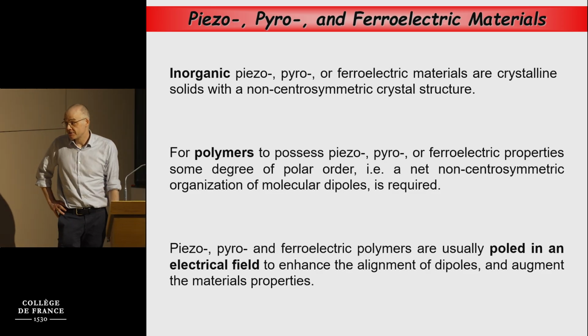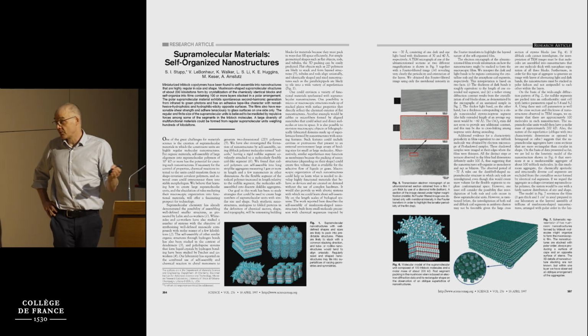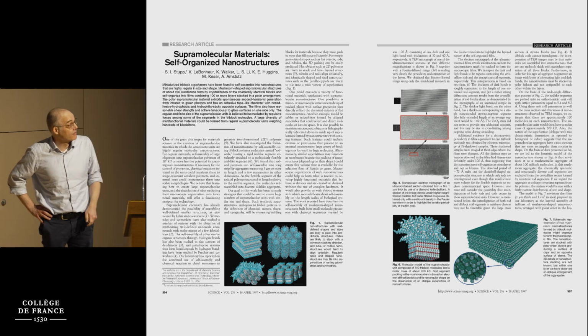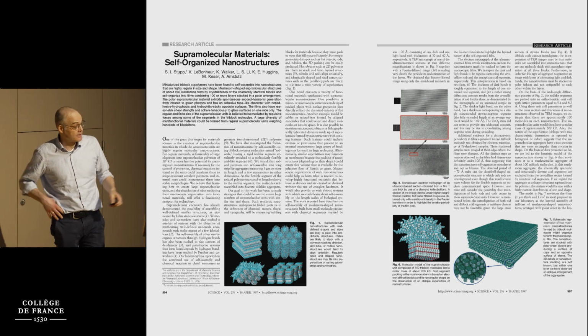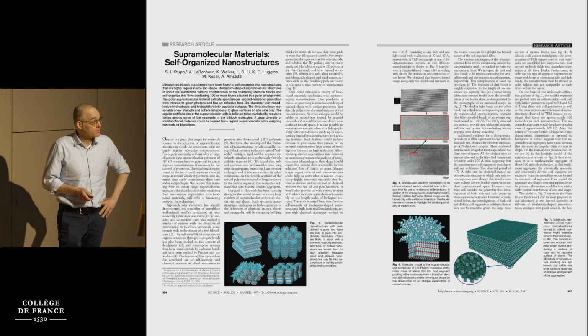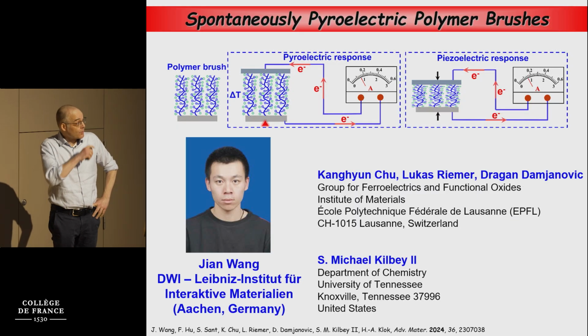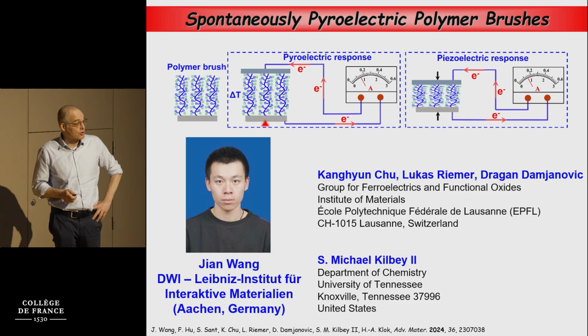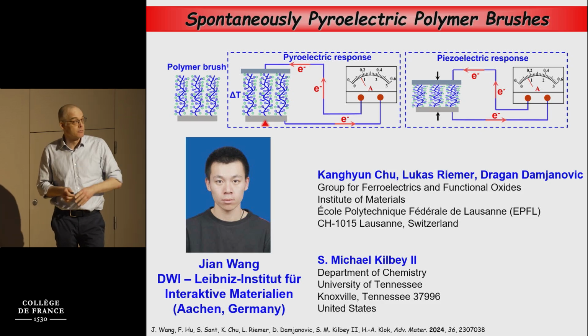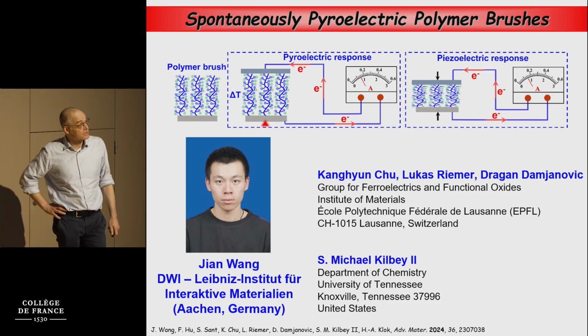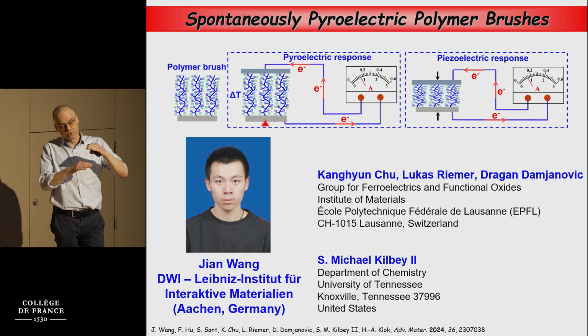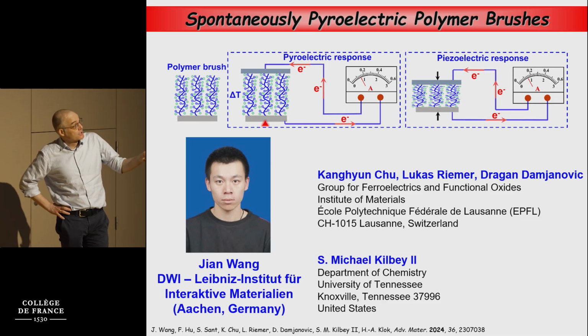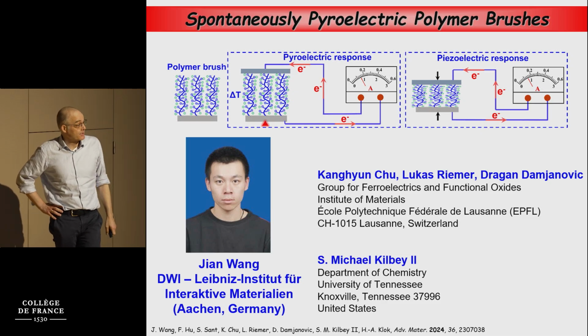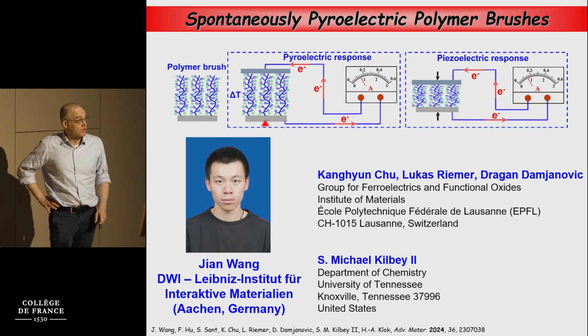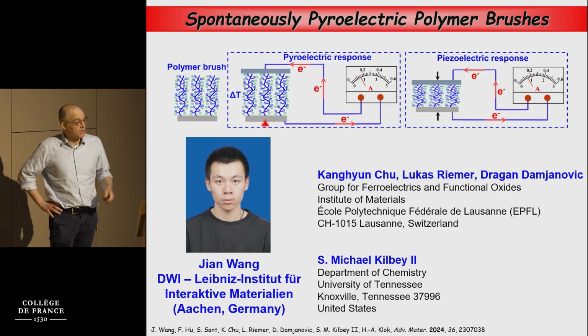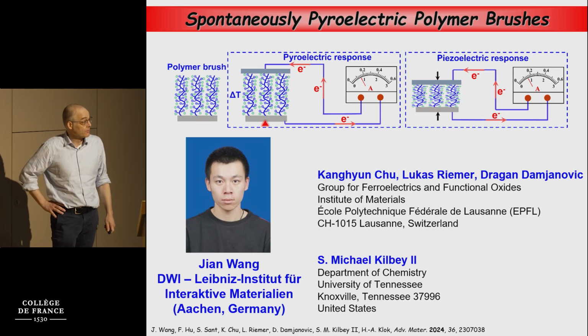One way to get around this is, if you don't want to work with polymers, you can work with organic molecules and use self-assembly strategies such as we've shown here. That's another way to obviate these poling processes. So what we accidentally found a couple of years ago was that if you grow thin polymer films via surface-initiated polymerization, this provides a route to produce very thin polymer films that possess pyro and piezoelectric properties. I'll walk you through a number of experiments that led us to this discovery, more or less.